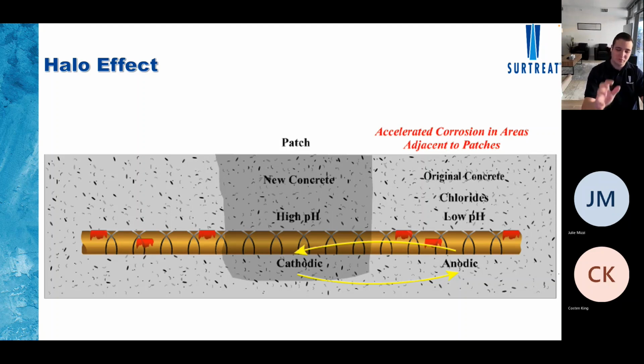What's happening is that you're putting a new patch, right, new concrete, which has high pH, which has all that nice reinforcement and that nice state, alongside corroded rebar or bad concrete that's contaminated with chlorides. And what's happening is that corrosion that's on the sides or on different areas, it's migrating back to that patch. So the cycle is repeating. Unless you treat the corrosion that's occurring in the rebar, you're going to have the same problem over and over and over again. And this is going to lead to increased costs.